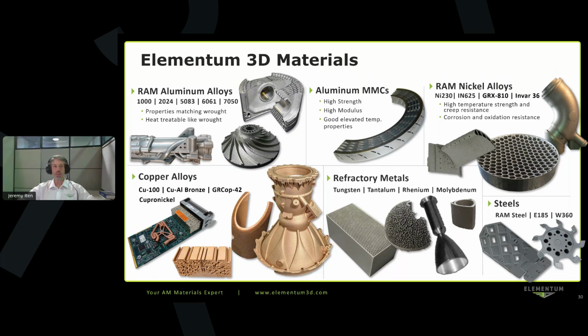And then also, we've done a lot of work with GRCop-42 together with NASA in commercial space and other customers. Cupro nickel together with the Navy and other commercial customers. And then we have a high operating temperature copper RAM product as well that maintains the properties and performance at high operating temperatures with the good printability. We've worked a lot with refractory metals, tungsten, tantalum, rhenium, molybdenum, and alloys thereof, and also with steels.